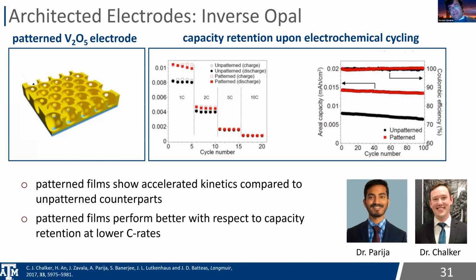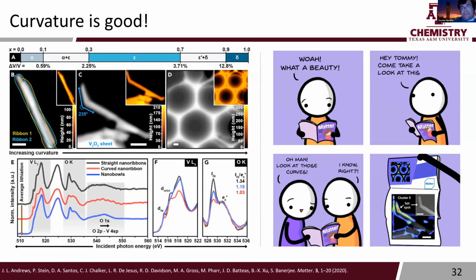So here's a way to start addressing some of these impediments to diffusion that arise from polaron formation and phase coexistence through geometrically texturing electrodes. Okay, so the takeaway message is that curvature is good. This is a cartoon that Steve Cranford posted for us on Twitter, and these curves are quite cool if you're trying to mitigate diffusion impediments.